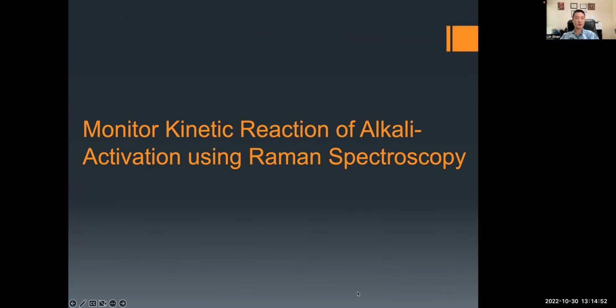And next, I will show how we can monitor the kinetic reaction of alkali activation using Raman spectroscopy. We can use Raman to do many things. For example, we can determine the phases of alumina, silica, and so on. We can analyze alkali activation at room temperature and also detect impurities such as calcite. But the most interesting thing is we can monitor the chemical reaction. We call that the dissolution process using Raman spectroscopy.